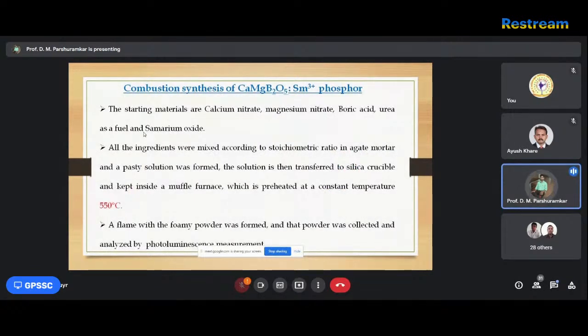For this purpose, for preparing my sample of CaMgB2O5, which is a samarium doped phosphor, I use combustion synthesis. Initially, I take the ingredients: calcium nitrate, magnesium nitrate, boric acid, urea as a fuel, and samarium oxide. Then I mix all the ingredients according to their stoichiometric ratio in the agate mortar, and a pasty solution was formed. Then this solution is transferred to a silica crucible and kept in a muffle furnace, which is preheated at a constant temperature of 550 degrees Celsius. After a short time, a flame with a foamy powder was formed, and then that powder was collected and analyzed by photoluminescence measurement.